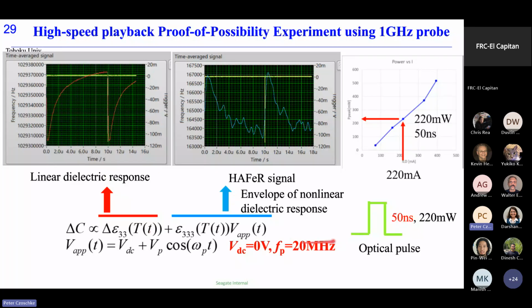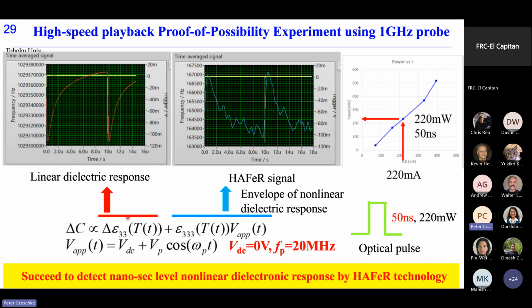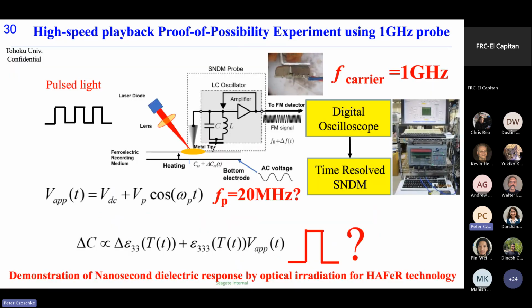Anyway, we increase the speed, or we decrease the duration of the pulse. So a very sharp optical pulse is applied like this, and the signal to noise is getting a little bit worse, but we surely confirm the HAFeR signal. And so we think that we have succeeded in detecting nanosecond level nonlinear dielectric response by the HAFeR technology.